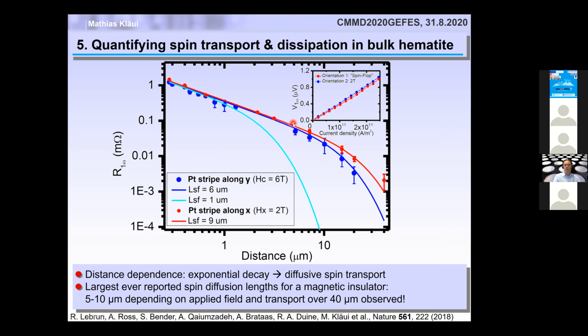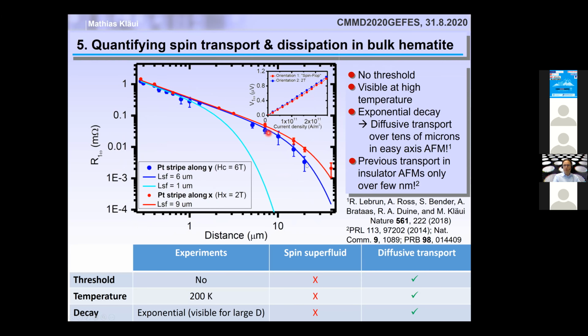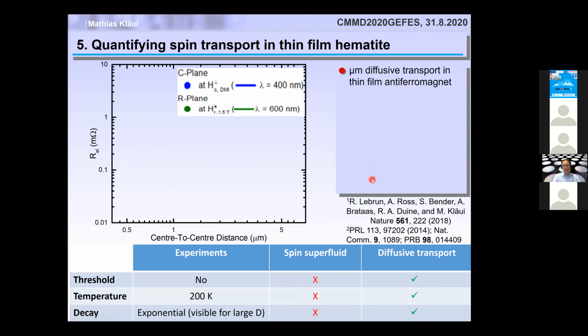And also what we could see is that, if you look closely at long distances, there is an exponential decay, and that shows you that this is really diffusive transport. So we don't see signatures of the predicted superfluid transport because there is no threshold. The temperature is relatively elevated where this works, and you have to measure at long distances in order to see this exponential decay. And previously, people only saw transport in insulators over a few nanometers. The question was why? So to check that, we actually looked at different surfaces and different thicknesses of the sample,